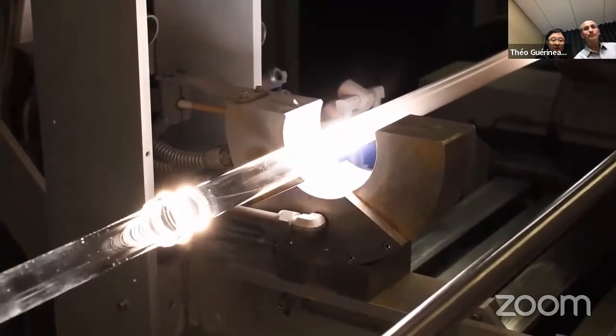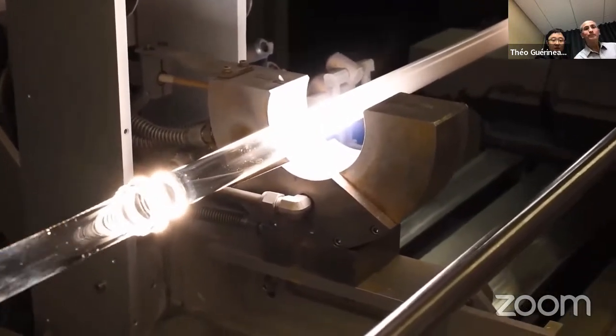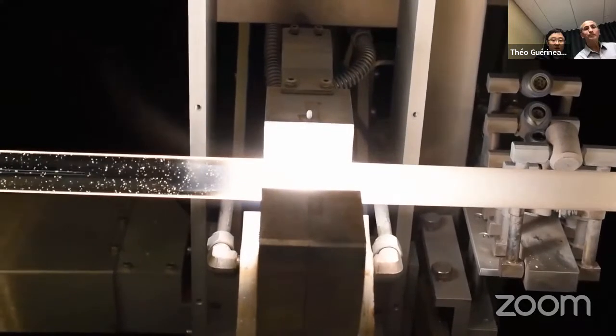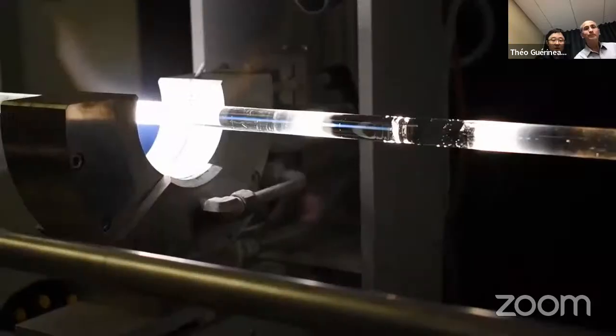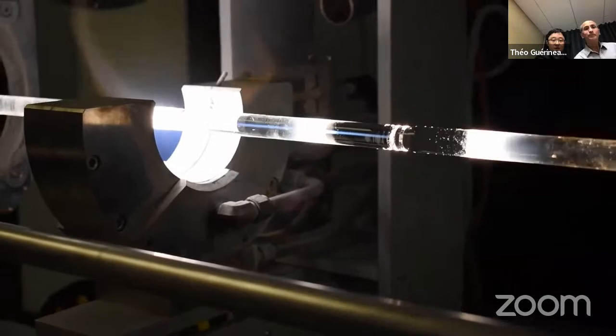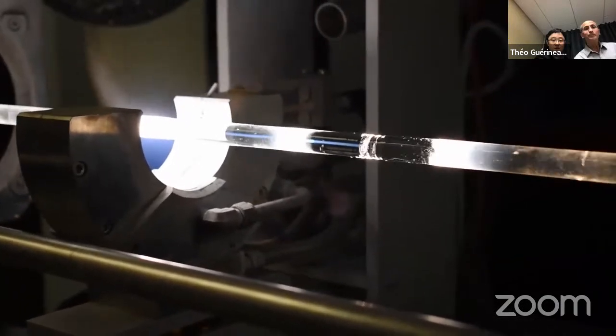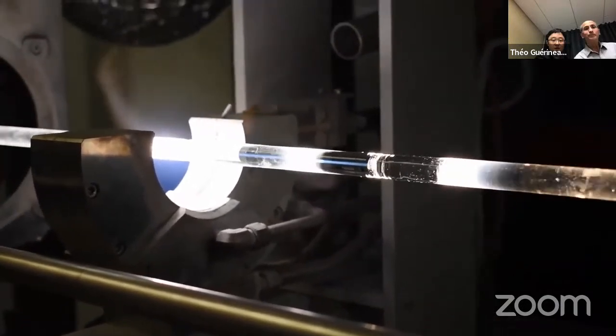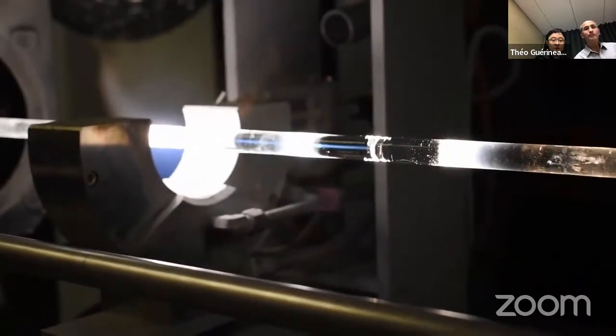The tube containing the soot is thermally treated to convert the porous soot into a glass layer. This step is followed by the tube collapse. The preform is almost ready. After cutting, the preform can be drawn into a fiber.